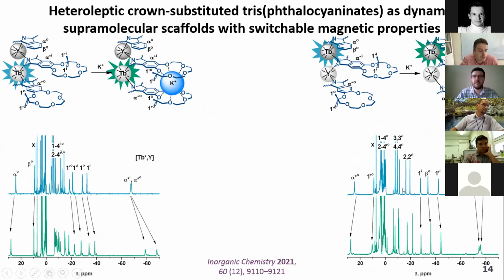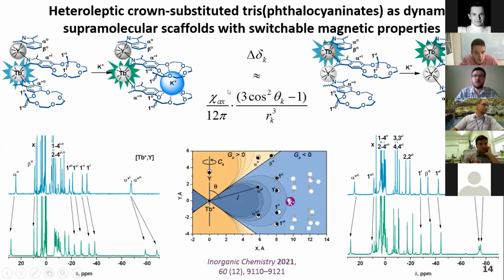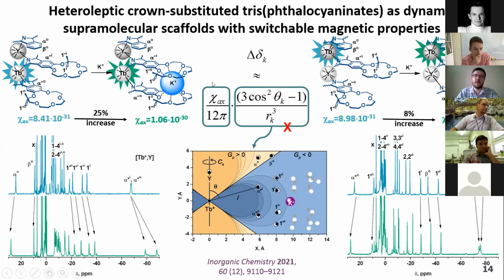But the same shifts, more or less the same order of magnitude, were observed in the case of the complex where terbium didn't switch its coordination polyhedron. Again, we used the powerful equation correlating lanthanide-induced shifts with axial anisotropy and geometry. Since we had the crystal structures of both states of this complex, we could see that, in spite of very strong rearrangement of molecules upon supramolecular interaction, the polar coordinates of protons do not really change. Here the black are the normal state, and white are states with potassium ions. So alteration of geometry is not enough to explain the observed shifts in NMR spectra. The only thing left is to explain it by increasing axial anisotropy.